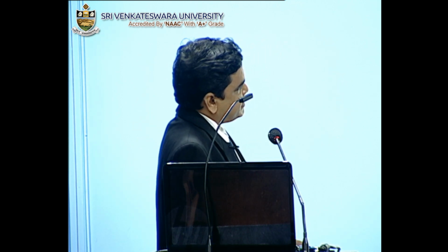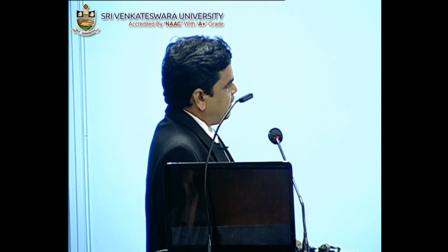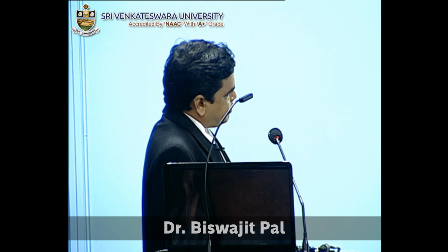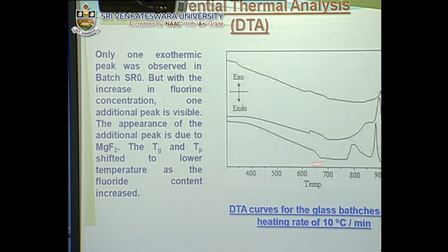Now when we varied the fluoride for SR0, only one exothermic peak appeared, and if we increase the fluoride content, an additional peak appeared, and this additional peak is due to magnesium fluoride. With increasing the fluoride content from SR0 to SR10, both the crystallization peak temperature and the glass transition temperature decrease, that is, they shift towards the left.